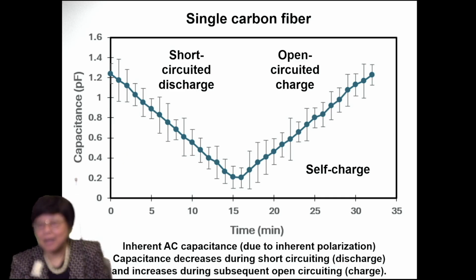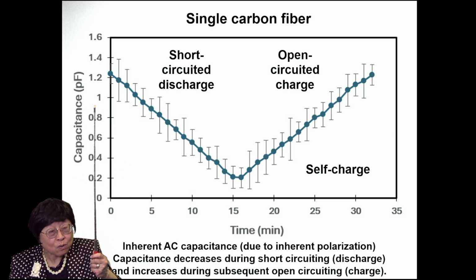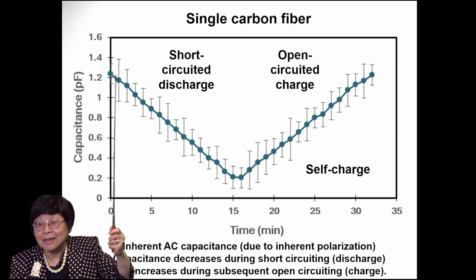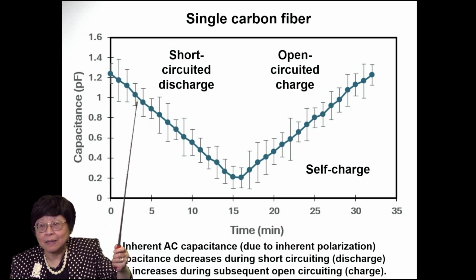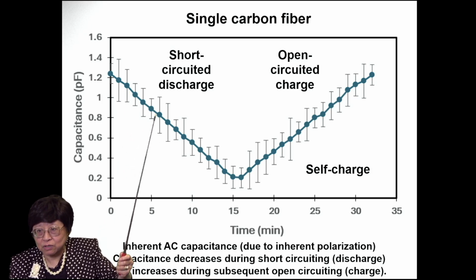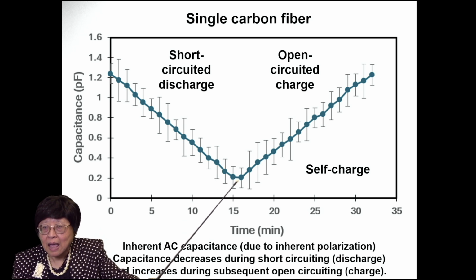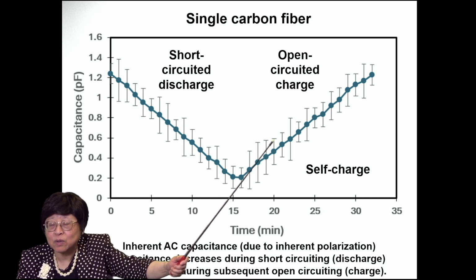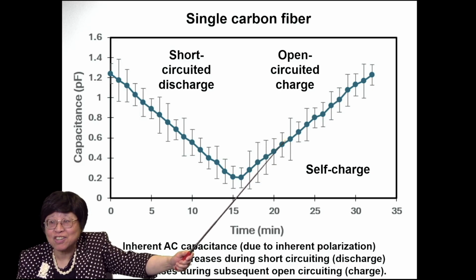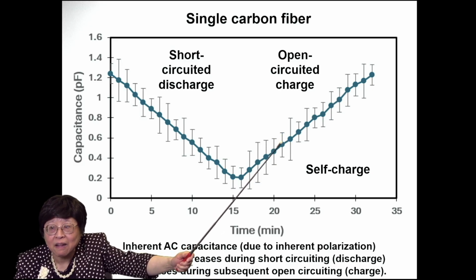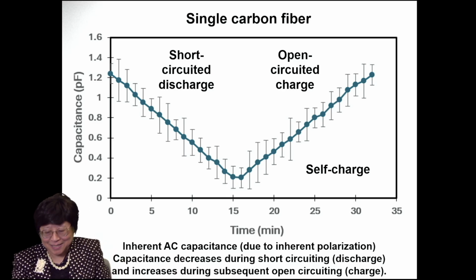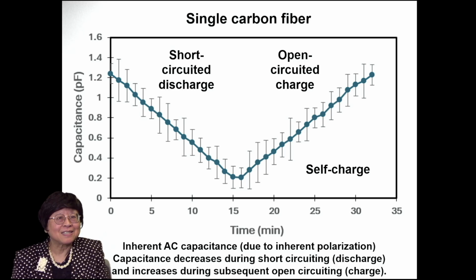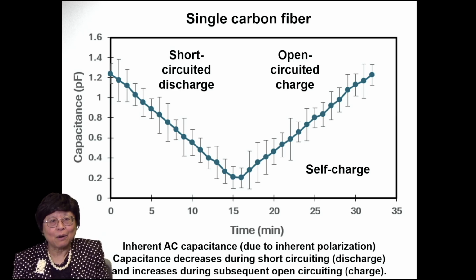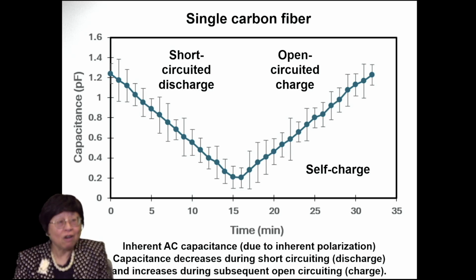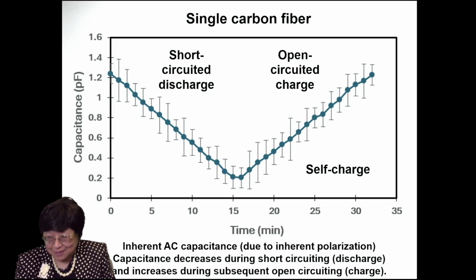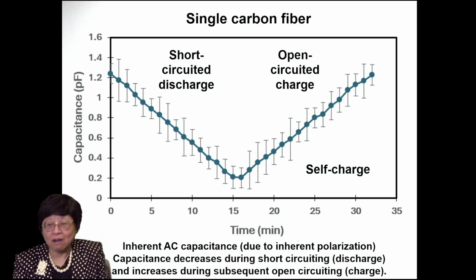And so this is a single carbon fiber. It exhibits capacitance without the need for poling. But if you short circuit the two ends of the single fiber, it would discharge, with the capacitance going down. Afterward, if you just open circuit it, it would self-charge. That is, it charges on its own, just sitting there open circuited. So it's self-charge. This is really revolutionary. Batteries and capacitors, conventional ones, all undergo self-discharge. And charging requires energy input, but this is just the opposite. The discharge is spontaneous, but the charge is self-charge.